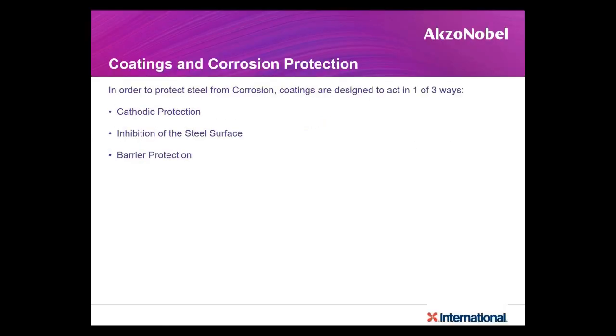Whenever we have corrosion, there are several methods of corrosion protection. We are seeing cathodic protection was one way. Then we have also coatings. You have coatings which are applied on steel to protect against corrosion. Now, how does this work? How do coatings protect steel from corrosion? There are three methods. One is called cathodic protection, in which the coatings have sacrificial anode-based pigments. For example, zinc dust is added in coatings that will act as a sacrificial anode. When this paint is applied on the surface, zinc will preferentially corrode, thereby protecting steel.